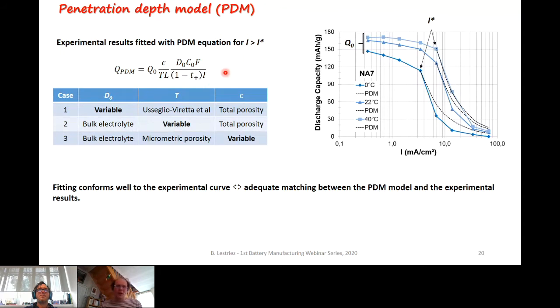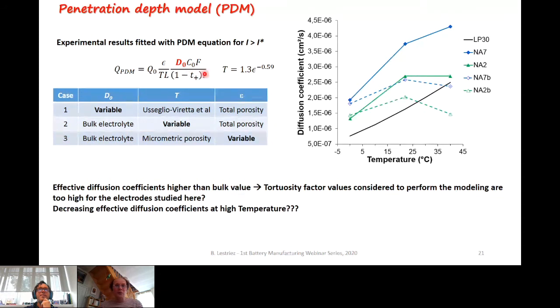But what we have decided first to do is to do the fitting by fixing some variables and allowing one of the parameters to vary, to really nicely match the experimental data. And we started with the diffusion coefficient. So we have done the fitting considering the total electrode porosity and considering either the tortuosity factors determined by numerical simulations, or taking values from the literature.